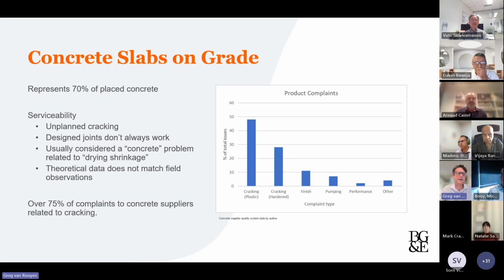Clearly, as discussed already, the data we get doesn't really match a lot of our field observations. And from my time in a concrete supplier, dealing with complaints, I'd say if you did a Pareto chart of crack complaints, really plastic cracking followed by longer term shrinkage cracking make up at least 75% of the types of complaints that concrete placers or concrete producers face every day.